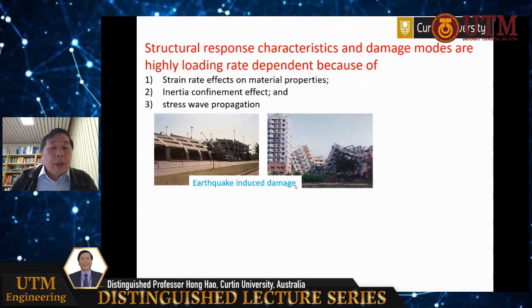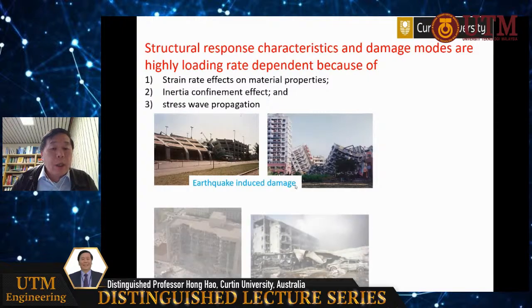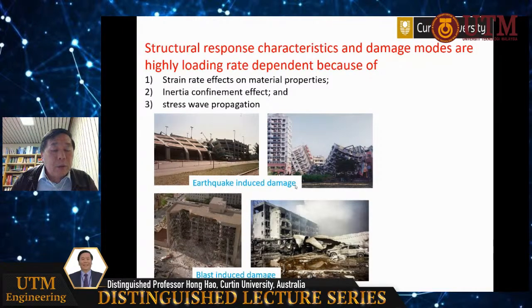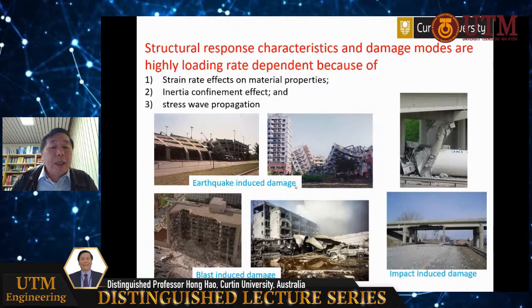So this is earthquake damage. Under earthquake excitation, we see very large drifts of the floors and stories, and overall collapse of the structure. But under blast loading, you might have a collapse, partial collapse, or progressive collapse, but the structure basically stands vertically. You don't see lateral drifts. And the same goes for impact load.